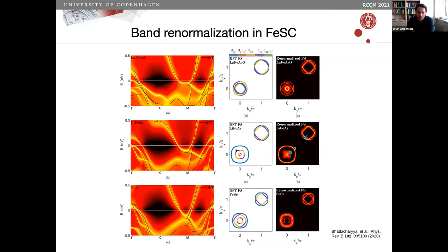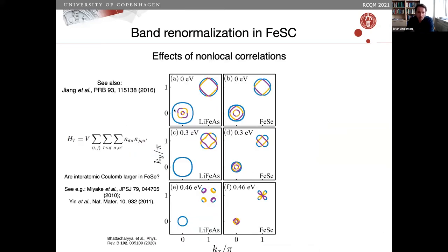The results of doing such a calculation for LiFeAs and iron selenide are: yes, there is such a pocket shrinking — the mechanism is there. You can compare the bare bands and the renormalized ones in yellow; this is just the spectral function calculated here, so there's a general shrinking. But the whole point is that for iron selenide this doesn't work — this mechanism is not capable, as far as we can see, of getting the right pockets in terms of number and size.